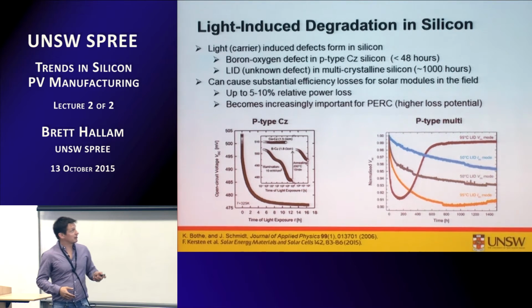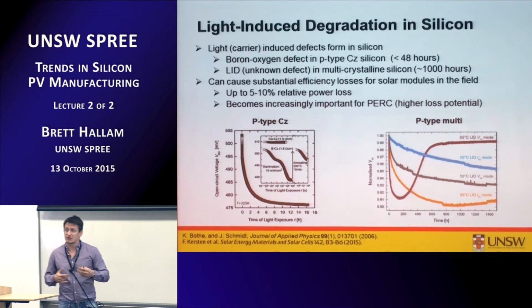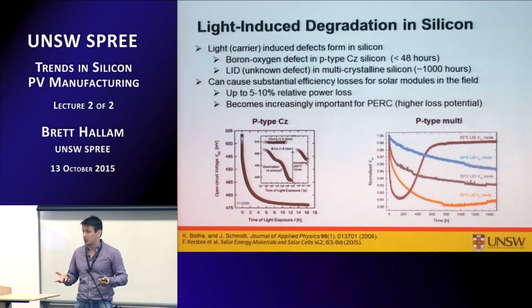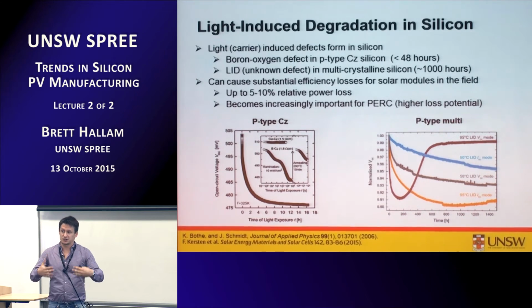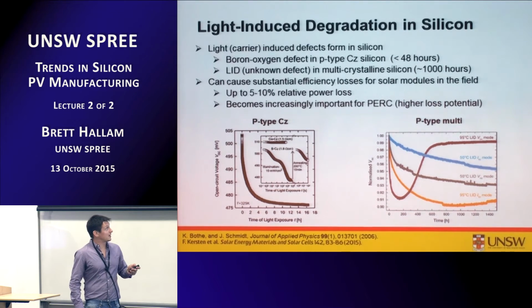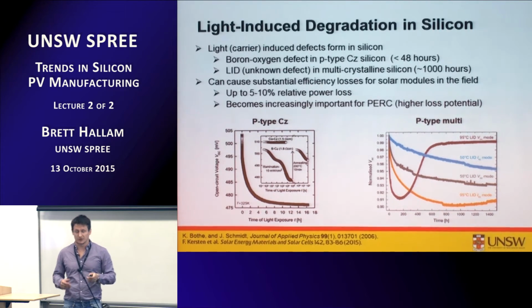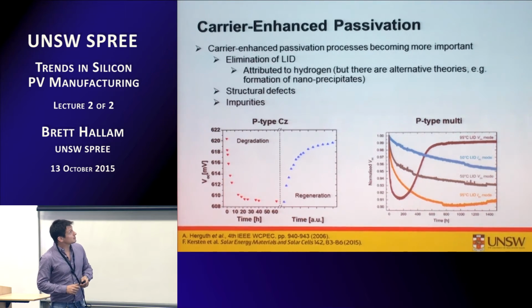And all of these carrier-induced defects have increasing potential efficiency losses as we move to the higher efficiency cell architectures like PERC, because as we increase the efficiency, even with the same concentration of a defect, it can have a strong influence on the recombination within the material. So it's becoming more apparent now with PERC. And some of these defects can cause 5 to 10% relative performance losses.